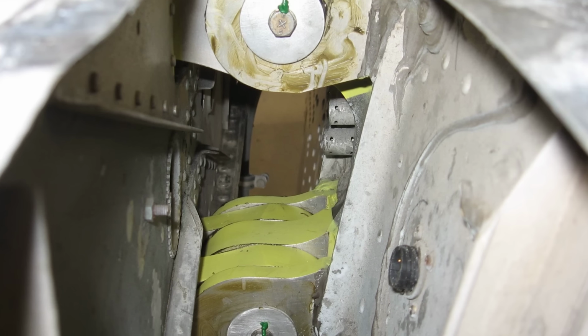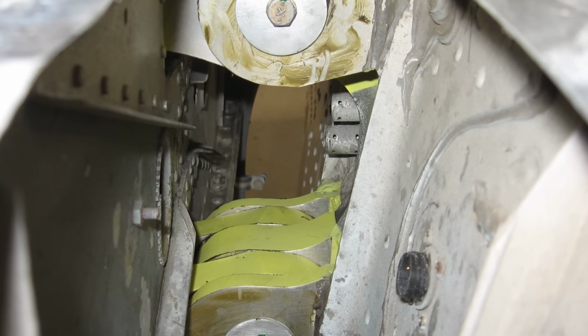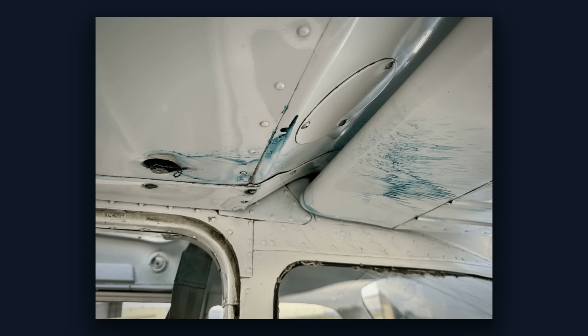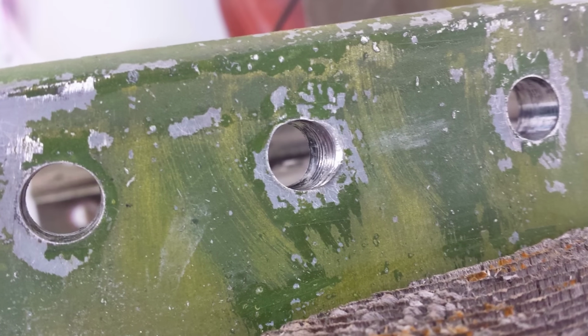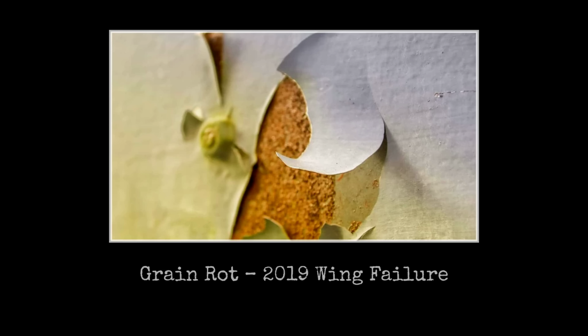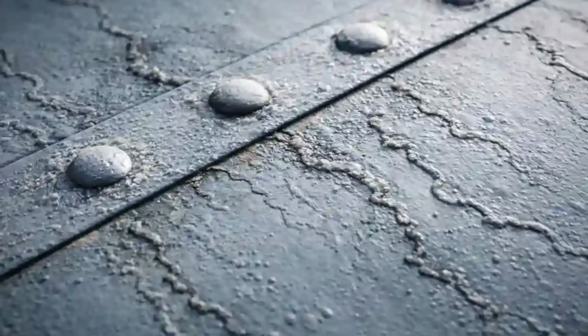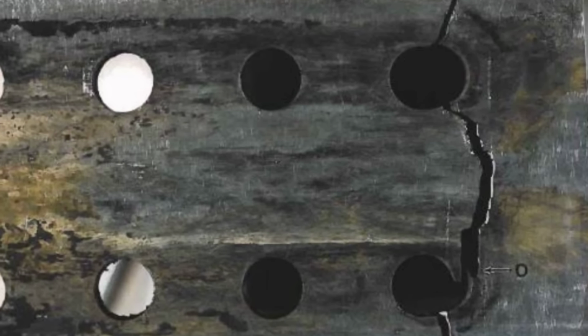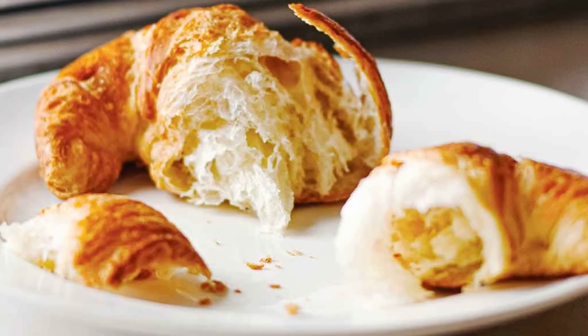In the name of cabin comfort, Cessna glued foam padding right up against the main spar. That foam acts like a sponge, soaking up every drop of condensation that forms inside the roof. For decades, moisture sits pressed against bare, high-strength aluminum. The result is not just surface rust. This is intergranular corrosion, the kind that eats along the grain boundaries and turns solid metal into flaky layers. Exfoliation. It looks like a croissant pulled apart.